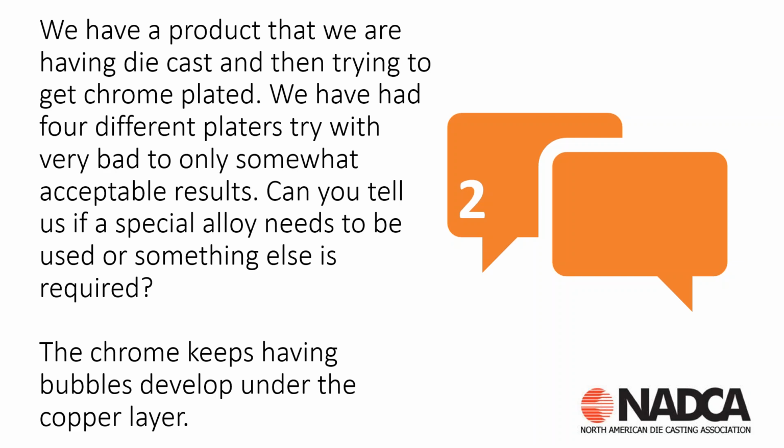So the question is, we have a product that we are having die cast, so they're an OEM, and then they chrome plate the parts. They have had 4 different platers try with very bad to somewhat acceptable results. Can you tell us if a special alloy needs to be used or if something else is required? Basically, the chrome keeps having bubbles develop underneath the copper layer.